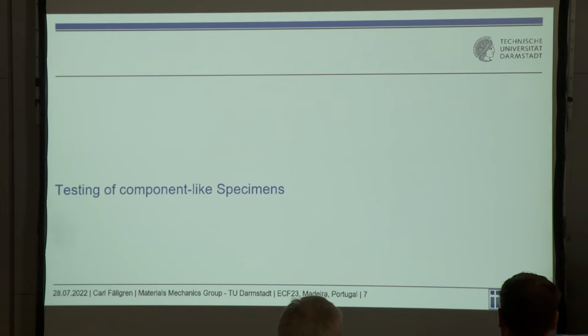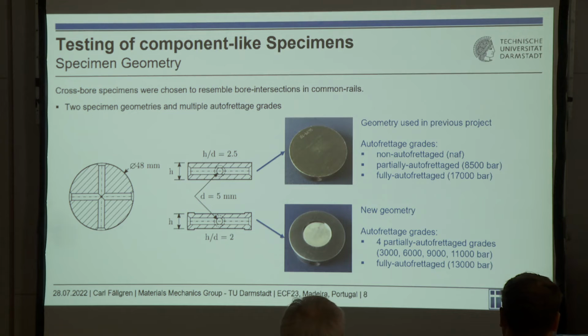So then we also performed testing of component-like specimens. What do those look like? We have this kind of specimen here, like a cross-bore specimen, and it resembles those bore intersections that you have in, for example, this common rail system. We had two specimen geometries, and we also tested different autofrettage grades.